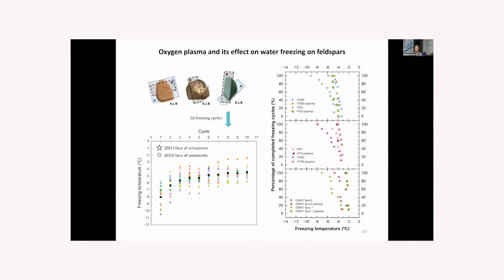But when we used the oxygen plasma to activate the surfaces, we could see even better performance of the cuts. It showed very stable freezing temperatures. You can see that the percentage of completed freezing cycles is always at the same temperature, like here -2 degrees C, the freezing point, and it was stable, and there was no trend of it starting at better freezing temperatures.